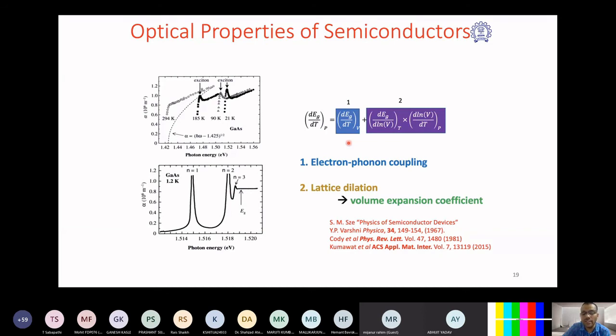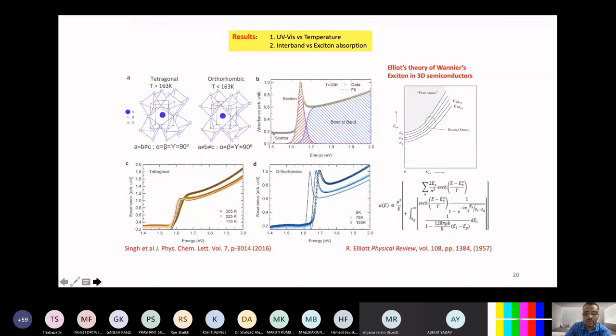Perovskite is a semiconductor, an ionic semiconductor, where you find things the other way around. As you increase the temperature, band gap is going to increase, not going to decrease. So your temperature coefficient of the band gap is positive, not negative, which is known from your textbook knowledge. Textbook says temperature coefficient of band gaps are negative because electron phonon interaction reduces the band gap as you increase the temperature. And that is not the case with the perovskite and some of those specific inorganic semiconductors, which is what is being shown here.